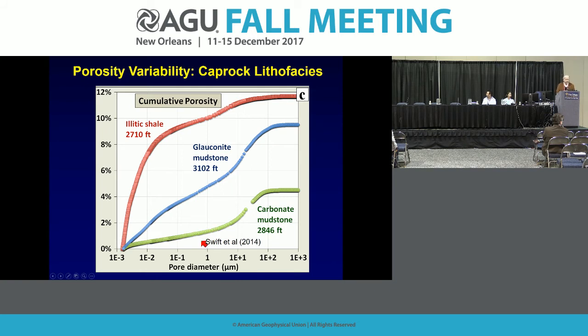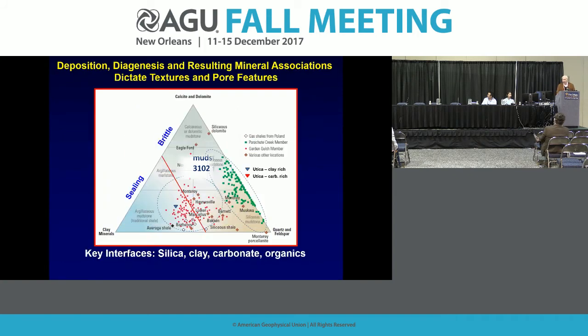But one take-home message I'd like you to keep an eye on is, if you notice these humps and this little bit of a dip, another hump, there's actually a picture forming in our mind now about some of these shales, particularly the ones that contain high clay, that they are bimodal in terms of their pore distribution. You certainly get a sense of this with this reach here and then a little bit out here, a coarser scale. The carbonate mud, we don't see that in. So again, we have this interesting scenario where we have a somewhat bimodal distribution of porosity, based on how the rock is stitched together in its fabric.